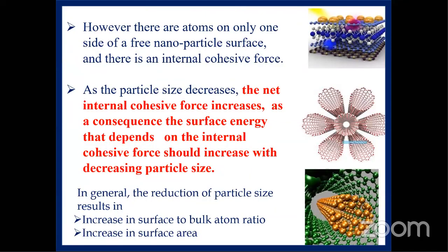You can see another one. You can see this is graphene and carbon nanotube. These layer structures have unusual properties because, as the particle size decreases, the net internal cohesive force increases. As a consequence, the surface energy, which depends on the internal cohesive force, should increase with decreasing particle size. When you reduce the particle size, the surface energy increases.